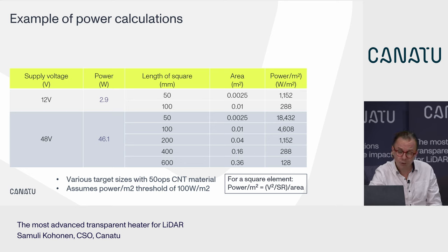If we have 48 volts as input power, of course, the power density increases significantly. We are able to create up to 18 kilowatts per square meter power density for this application where you have an electrode distance of 50 millimeters. So basically with this 18 kilowatts per square meter, you are exploding the ice away immediately. The values I'm presenting here are based on 50 ohms per square CNT material, which is a rather typical application for us and our customers.